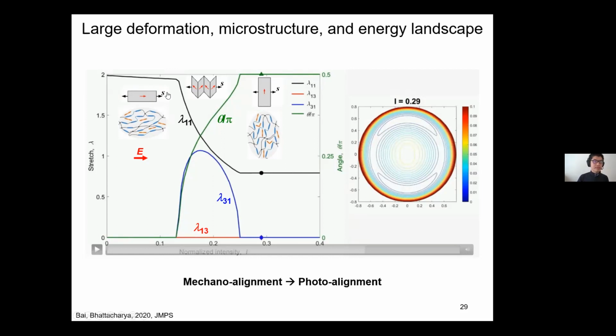If you trace the deformation, initially it aligns with the stress, very large deformation, lambda 1,1 stretch, and then it decreases and becomes shortened, okay? And what's more interesting is in the middle, in this transition period, I have a finite shear strain. What you can usually observe in this liquid crystal elastomer is this shear strain can be either positive or negative. Because of boundary conditions, these positive and negative shear strains can stack to each other and form the so-called stripe domain microstructures. These are all very interesting phenomena we observed using the model.